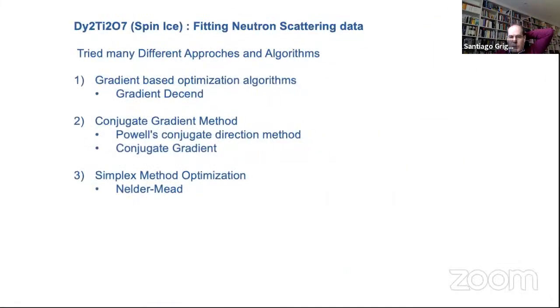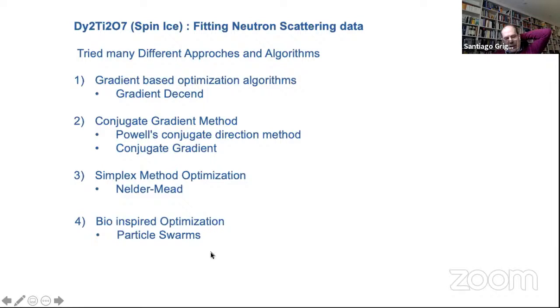Right. So then what we did was essentially something where one would say it's quite simple. We took that long Hamiltonian, we simulate it, and we try to fit the parameters so that the calculated neutron diffraction would match the experimental neutron diffraction. And okay, so we tried many different approaches, and so 1, 2, and 3 didn't really work, in the sense that there are so many different minima that we're talking of some sort of a 5-parameter fit.